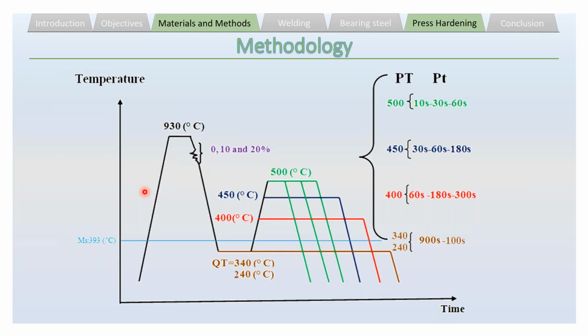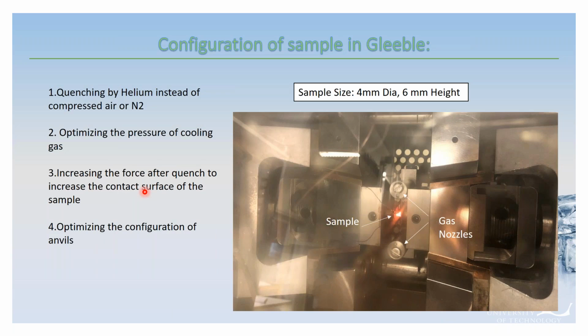And the last one, which is an ongoing project, is about hot stamping. We have used the settings which are used in Gestamp. This is a hot stamping company in Luleå, and we have a good collaboration with them in this project. You can see that we have used a very tiny sample first in Gleeble. The sample size is 4 mm in diameter and 6 mm in height. So they are cut from a 6 mm sheet. And then you can see the gas nozzles, which we have used for cooling to a quenching temperature. This work has had different difficulties using Gleeble, and thanks to the Gleeble staff, we figured out how to simulate the hot stamping process.